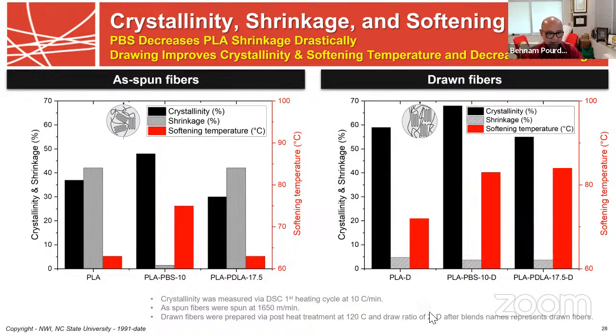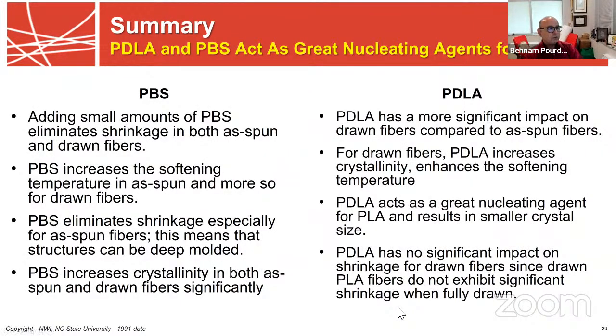And then what this means is that a lot of the challenges that we've had with these materials really go away by just doing some very simple blends. So if you look at the summary of what I presented, adding small amounts of PBS eliminates shrinkage in both spun and drawn fibers. It enhances the softening or heat deflection or heat distortion temperature in both undrawn or partially drawn and fully drawn fibers. It eliminates essentially shrinkage and increases crystallinity very significantly. And more importantly, it actually eliminates that cold crystallization that happens with the pure PLA.